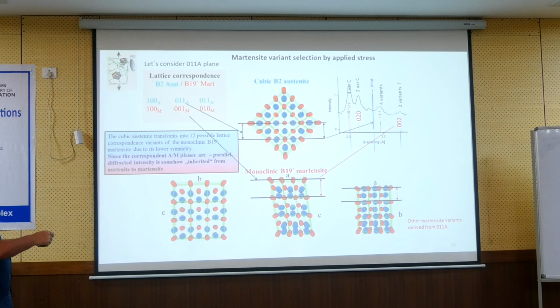Because of the lattice correspondence, if you have the austenite to martensite transformation, the intensity of this peak will decrease and this will increase. But if I have the transformation upon cooling, other variants may form too, and in other variants the 011 plane will change to this one, which has smaller lattice spacing. So it has the peak here. So now from one austenite I have two martensite peaks.